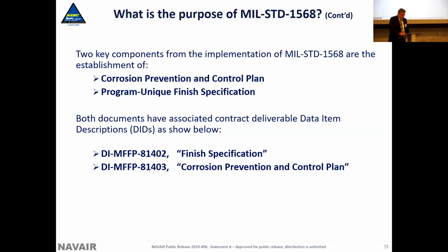If someone were to ask me what are the two key components from the implementation of Mill Standard 1568, I mean, not only does it give the lessons learned to avoid corrosion, like it'll tell you, don't put a nickel coating on top of aluminum, because the nickel coating is cathodic, and the aluminum is anodic. So if you get a little break in the surface, because of the big difference between the potential, you're going to get a huge extreme corrosion of the aluminum. So that's one of the things covered in 1568, the lessons learned, but also mainly the two key components from the implementation of Mill Standard 1568 are the establishment of a corrosion prevention and control plan and a program unique finish specification.